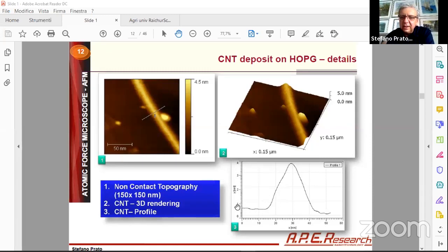First of all, what you need is the Z resolution. As you see here along this profile, if you measure from here to here, the size of this tube is around 2-3 nanometers tall, around 3 nanometers. So it's quite shallow. And with AFM you can really measure this with a very nice accuracy.